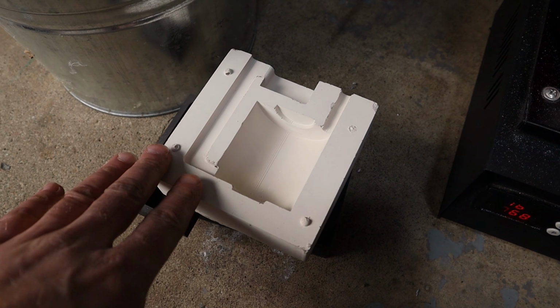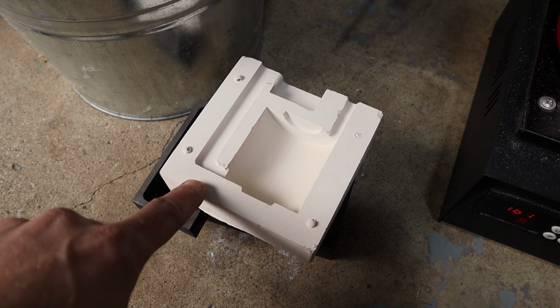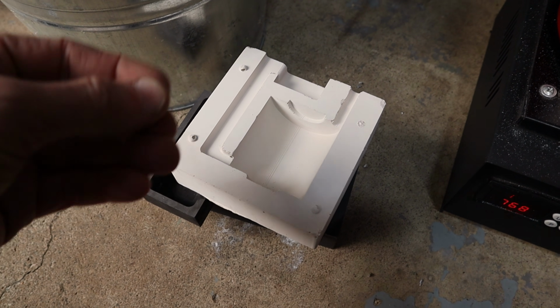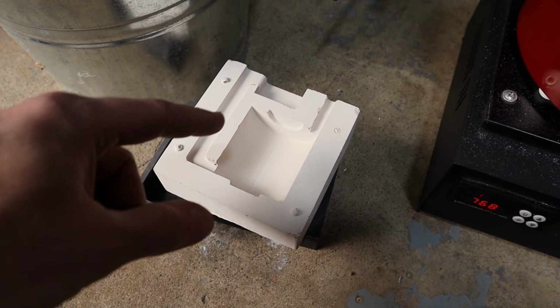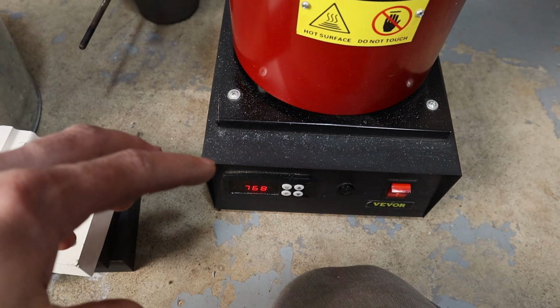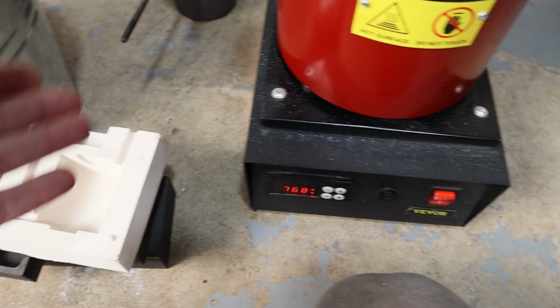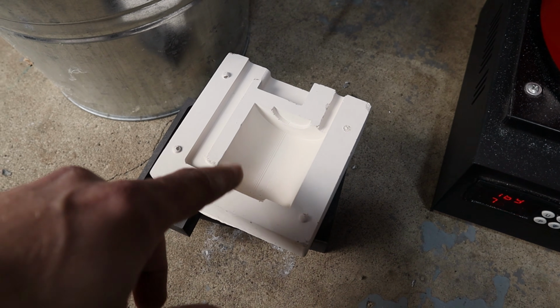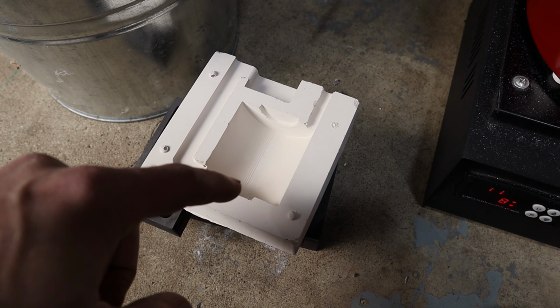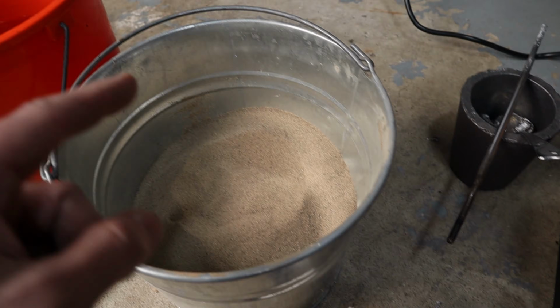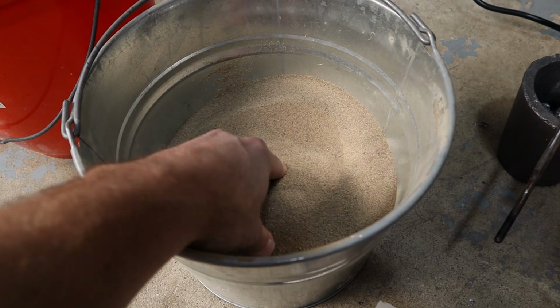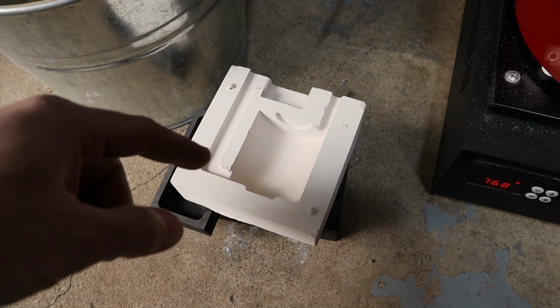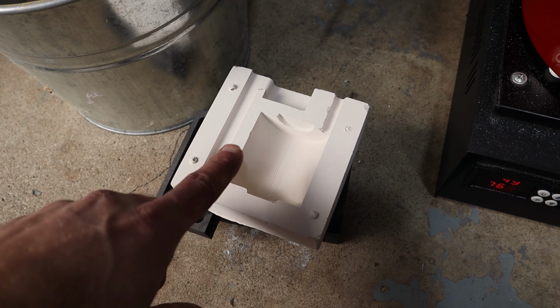And the other benefit of a mold like this is if we can keep the mold really hot, I'm trying to get it around 200 or 150 degrees Celsius, we're going to be pouring in around 700 degrees Celsius or 725 by the time it's coming out into this mold. So it's not going to cool it down as dramatically as if we're pouring into, for example, sand, which is just at room temperature.